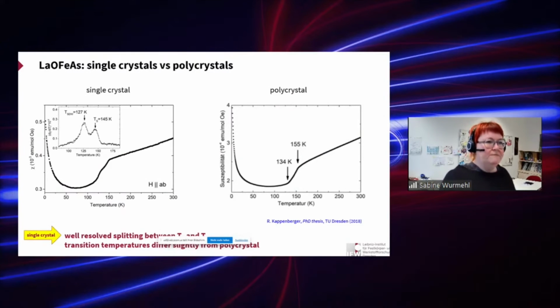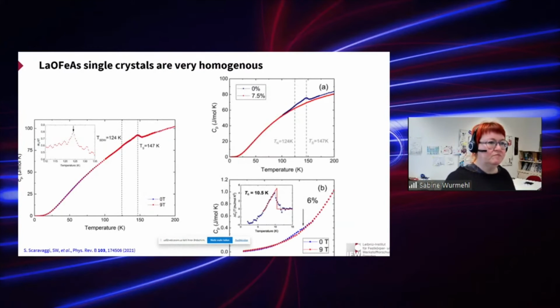And we clearly prove that we are dealing with the 1111 structure that we want to have. If you compare the single crystals and the polycrystals, you can see that the structural and spin density transitions are shifted a little bit to lower temperatures, which may be related to an oxygen deficiency in the single crystals. But nevertheless, the transitions are very well resolved in the single crystal materials, much better than in the polycrystalline materials. You also see the transition for the parent compound very well in specific heat.